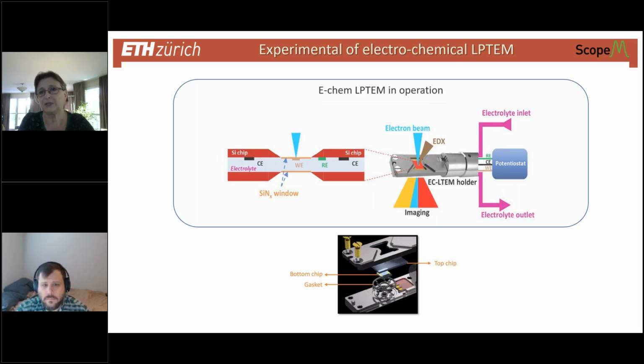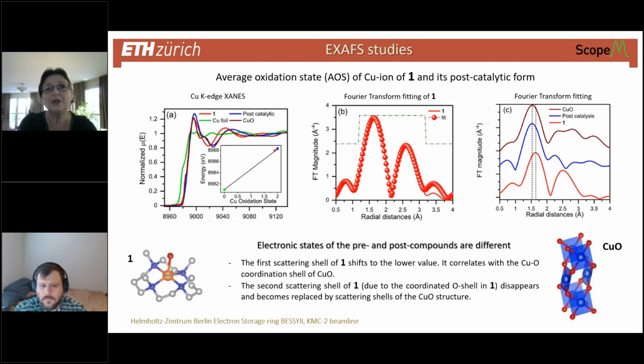So I relied on the size of the window when I assembled the whole sandwich under the binocular. It's just experience probably. If you do it X times, on X plus 1 you already have the hint. So platinum was easy from this point of view, and of course from the contrast immediately in TEM. For glassy carbon I looked for a few minutes, even with an aperture, to find it, and then you have to be fast, because once you focus or condense the beam to make higher contrast, you're always afraid to induce some changes, right? And you don't need much energy to initiate that.